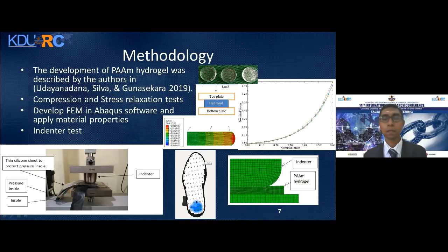And then the next test is to test this material with an indenter to simulate the heel of a person. Actually, here we use a pressure insole. The pressure insole was kept between the indenter and the material, so that we can get the surface pressure acting on this material. And a similar setup was modeled in the finite element software. Here I used a 2D axisymmetric model.